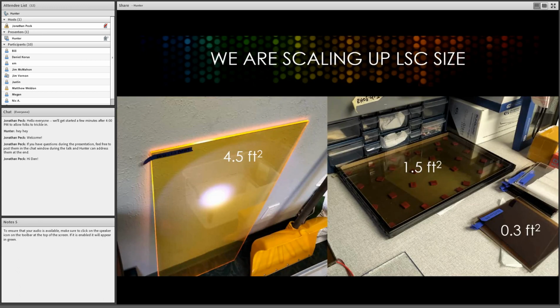Okay, so it's not just about does it work and is it stable, it's also can you make it big enough to actually make a product. And we're working on that. Our milestone is a square meter by the end of March. We've actually prototyped without dots, with some dye, by our manufacturing process at a square meter. But with the dots, we've made up to about 5 square feet. There's an example on the left with some visible dots, but we've also done it with some near IR dots like you see on the right.